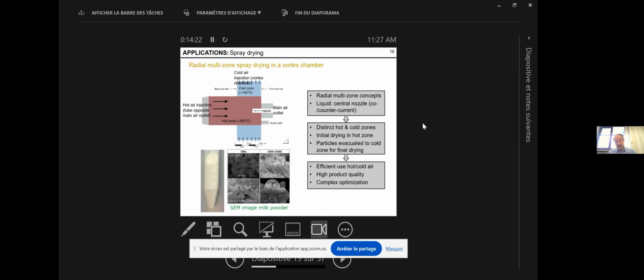And we try to use CFD for scale-up. It gives good qualitative information, but quantitative it is more difficult because you are dealing here with a very complex problem in fluid dynamics because of droplet size distributions and also particle size distributions as a result of that. And to model that accurately in the CFD code, CFD codes that work normally either with Eulerian description or Lagrangian, but then with pseudo particles, it is not so evident to capture correctly the drying process with the droplet and particle size distributions.